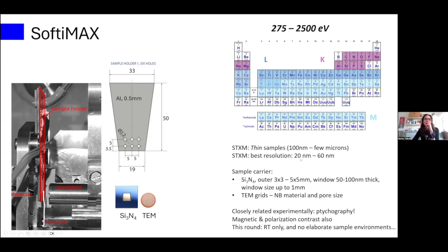The best resolution that we have for actual samples, more than just a proof of principle, for actual samples is 20 to 60 nanometers. But it is not something where you would say, of course, give me the best resolution. Think about what you need. Sometimes 50 nanometers is enough for what you want to see. So that is perfectly fine.